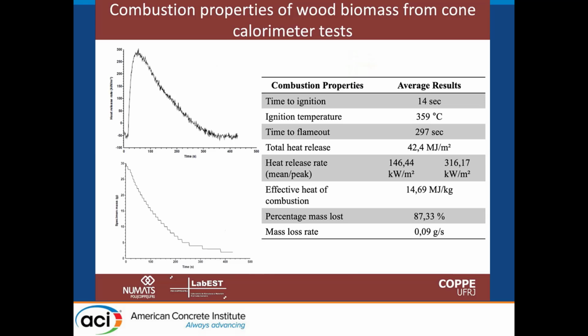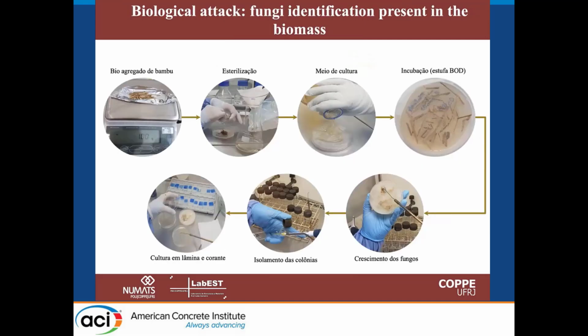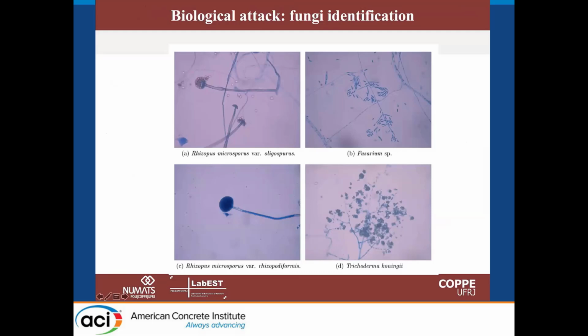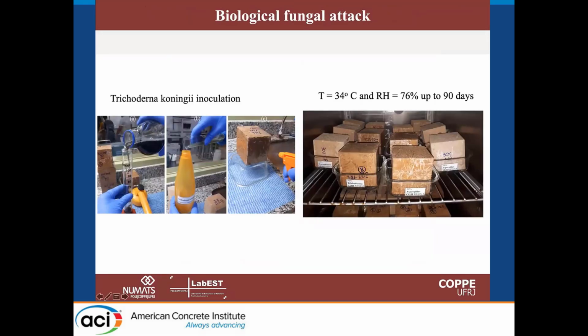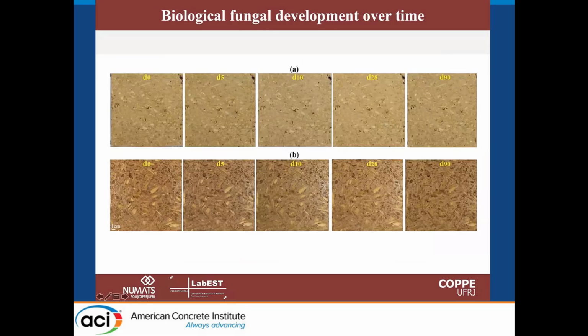no ignition was observed. Another important aspect is the biological durability of this material, because normally they have fungi, and we need to prevent fungal growth in the medium. So we identified for each biomass the kind of fungi that can be present in the biomass. And later we did the inoculation of the bioconcrete with these materials. We put this in a climatic chamber to simulate a microclimate, and then to see if fungi could grow on the surface of these materials. But as you see here, even up to 90 days, no signs of fungi were observed in a mixture that had 70% of biomass in the composition.